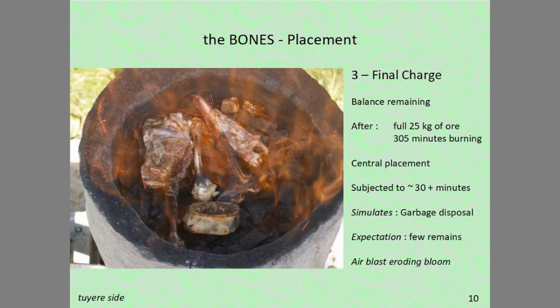The last addition of bone was made after all the ore had been added to the furnace. At this point, the body of the furnace had been burning for 305 minutes. There would be one final load of charcoal, 1.8 kilos, placed on top of this bone, and then the furnace would be allowed to burn down.